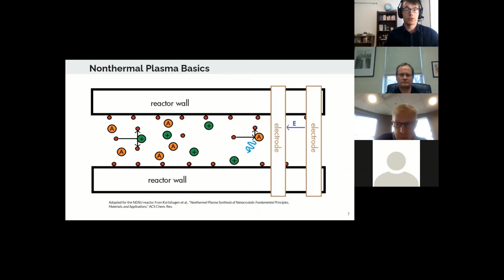When compared to nanoparticle synthesis by thermal DC plasmas, non-thermal AC plasmas, in our case we use radio frequency plasmas, can be several orders of magnitude lower power. Our NDSU reactor has made crystalline nanoparticles from as little as 12 watts of net power put into the plasma. At such low powers, the reactor does not even require active cooling to remain operable. This efficiency is even more advantageous for making silicon carbide because it is a high melting point material. Silicon carbide can be made directly in crystalline form in the non-thermal plasma, since the nanoparticles are heated by surface reactions. And those surface reactions come about because of the electron collisions.